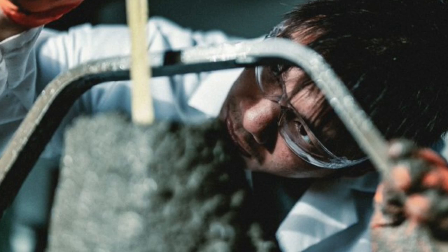The Meta researchers wanted to test the formulas in the field and selected their data center in DeKalb, Illinois as an ideal location given its proximity to the University of Illinois. After the final formula was tested in labs, the researchers agreed to test them on multiple non-critical structures at their data center, namely the guardhouse floor slab and the floor slab of the construction management team's temporary office space building. This refined concrete formula entailed upwards of 50% cement replacement with a combination of fly ash and slag.